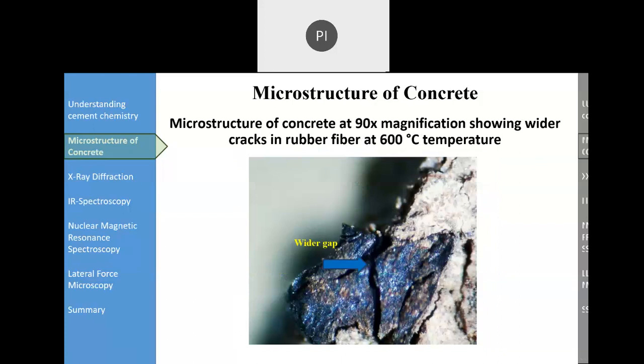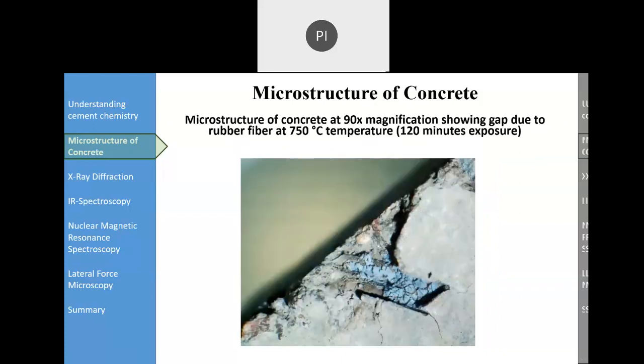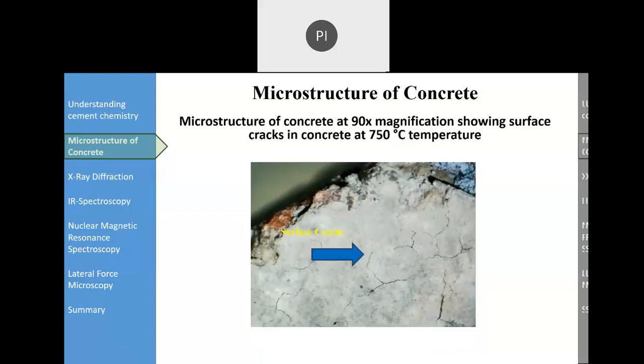And here you can see a clear cut gap between the rubber fiber and the other parts of the concrete when the temperature is up to 750 degrees centigrade. And you can see surface cracks also in the microstructure image.